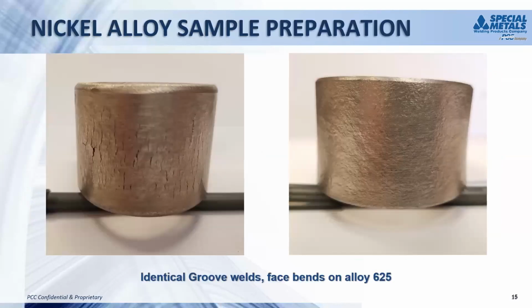Next slide. One of the last things that is commonly overlooked is the sample preparation of a nickel alloy. What we have in this picture are 2 identical 625 alloy welds. These would be the face bends that are typically required for qualification of filler metal. The one on the left was prepared at a brand new state-of-the-art lab that had really nice CNC machining abilities, but they had very little, if any, experience with nickel alloys. If you're not real familiar with machining, it's not uncommon with steels to remove as much as 1/8 to 1/4 of an inch on a single pass with the CNC machine to get these samples ready.